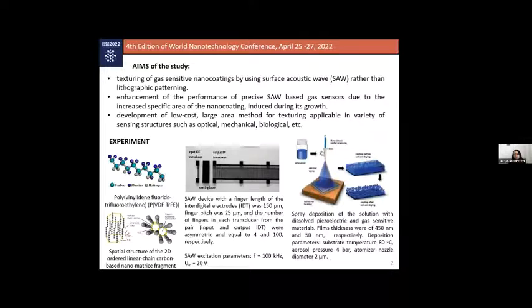So following the well-known methodology for design of such a device, a specific structure of interdigitated electrodes was produced, with an asymmetric pair of input and output transducers, which are designed in such a way as to guarantee that the acoustic wave is not quenched during the film growth.